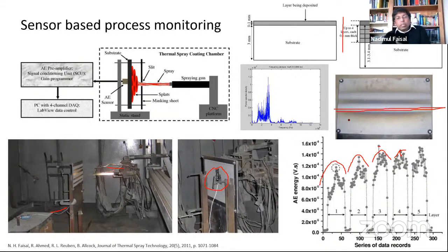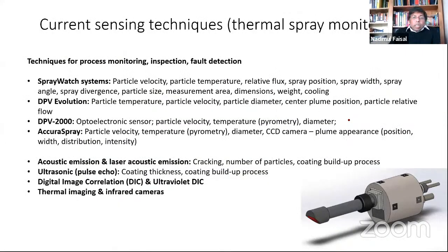However, we think that a lot of additional sensing methods can be deployed. You would know there are a number of techniques available. These are some of the techniques which are commercially available. They have deployed optical methods or pyrometry methods to measure a number of things like temperature, velocity, plume position, distribution, intensity, even weight. They can measure dimensions. Some of these techniques are not, I would say, commercially available because these are still in the R&D phase, but these can help measure cracking or the number of particles sprayed as a coating builds up. There are many other sensing techniques beyond this list which can be deployed with the gun or spray system to monitor the spray process.